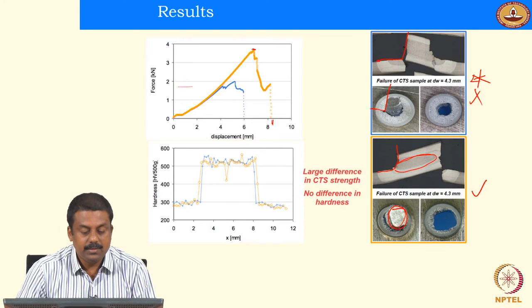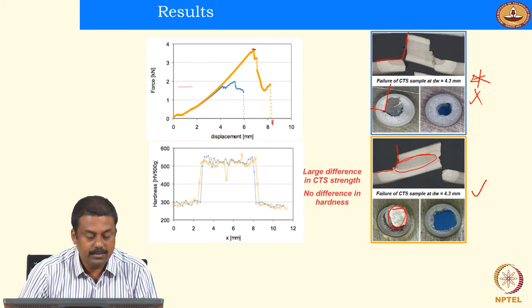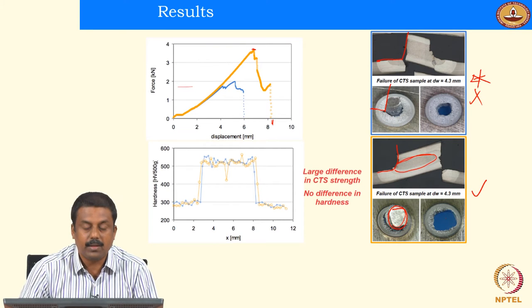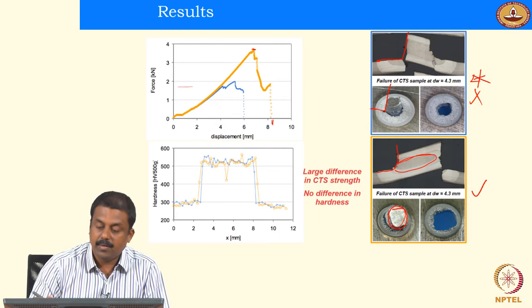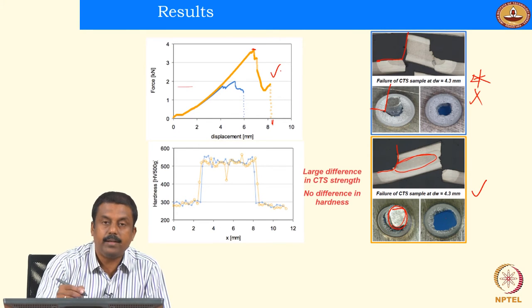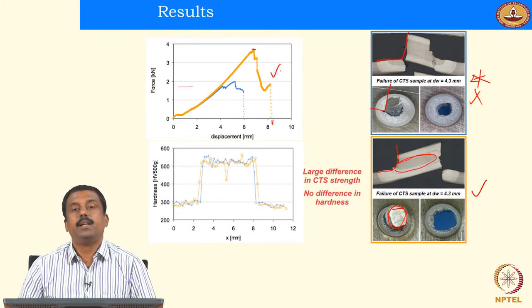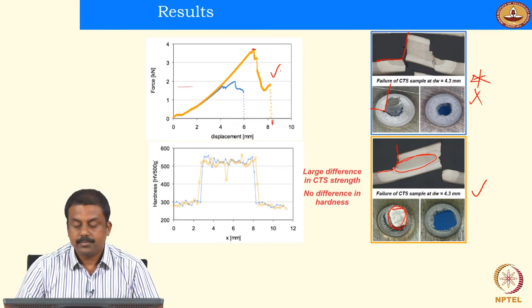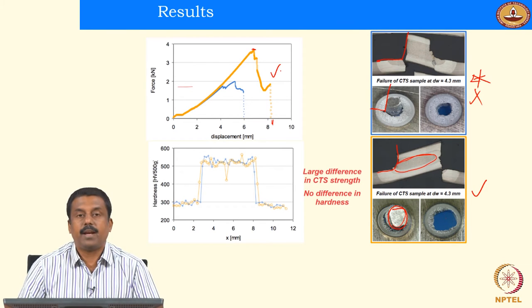But there is no significant variation in the hardness in both the cases. Both showed similar hardness variation. That means that hardness-wise there is no problem. But we have a significant improvement in the failure mode as well as the mechanical properties. That means that second pulsing is beneficial to improve the mechanical properties.